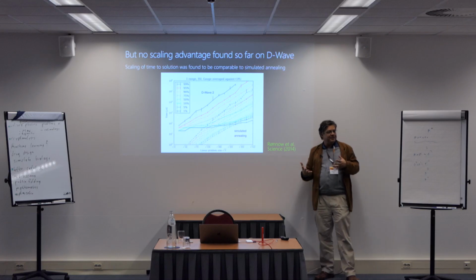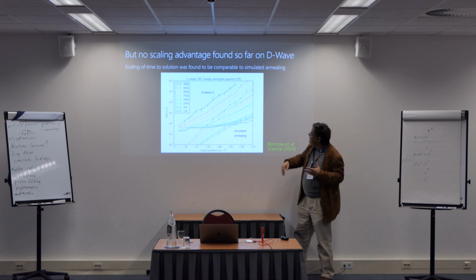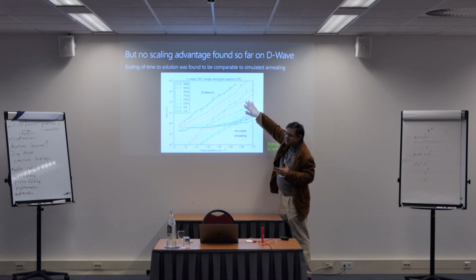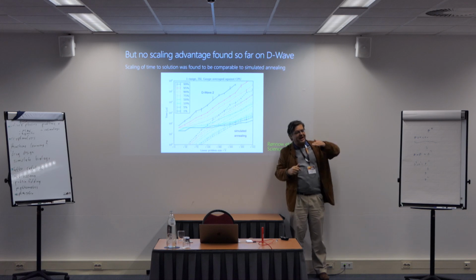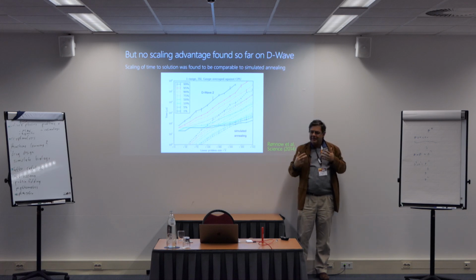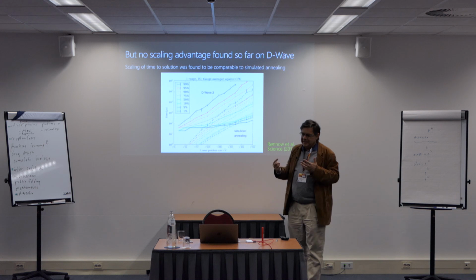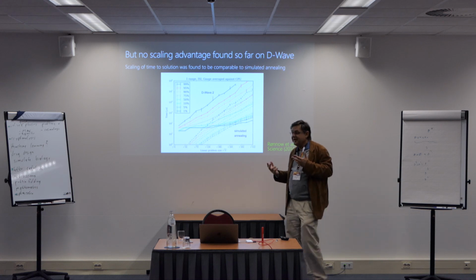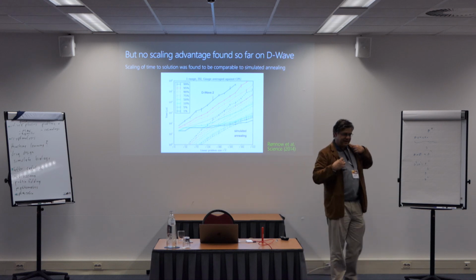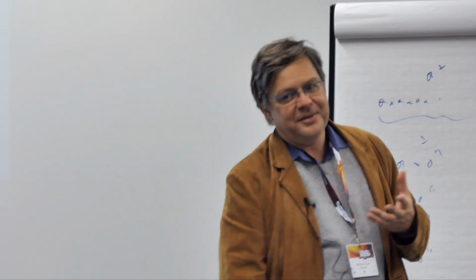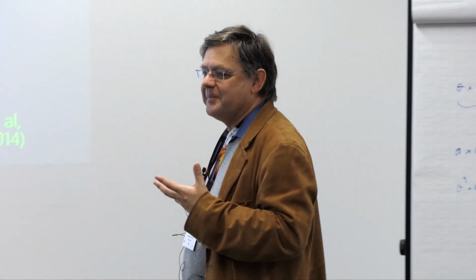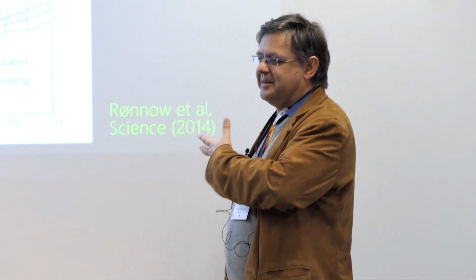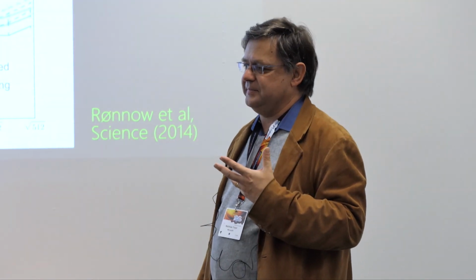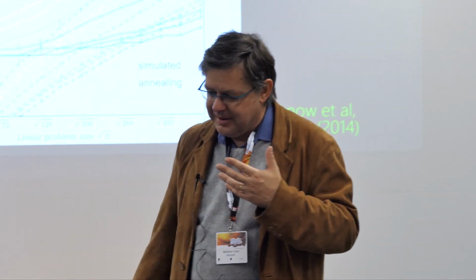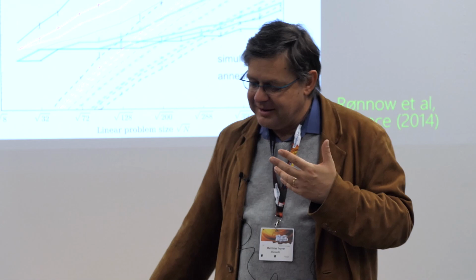If quantum annealing had been really faster, then I would have expected the quantum annealing curves here to asymptotically be flatter than the classical ones. But we didn't see that. And that was a question then. Why did all the theory and simulations predict that quantum annealing should be better, and we didn't see it in experiments? And so then we started looking at that.